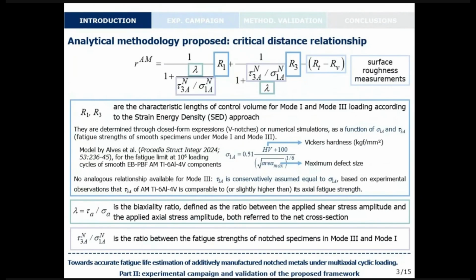And of course, it is a function of R1 and R3, that are the characteristic lengths obtained according to the said approach. These lengths are determined through either closed form expressions for V-notches or numerical simulations, but in both cases they are a function of sigma 1a and tau 3a, that are the fatigue strength of smooth specimens under Mode 1 and Mode 3 loadings. And here, in order to compute sigma 1a, we employ the model proposed by Alves et al., which gives this value as a function of the Vickers hardness and the maximum defect size of the material.